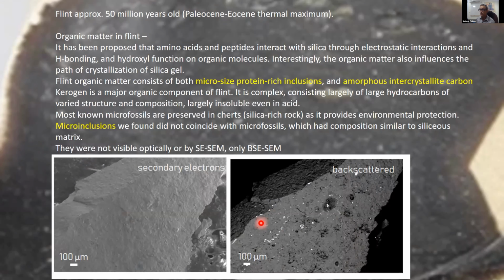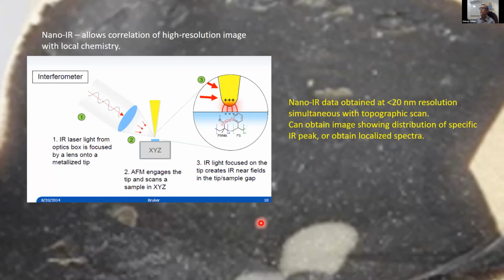The part that we're going to be talking about is these microinclusions. They're hard to see. You don't see them optically. You don't even see them in electron microscope with the secondary electrons, but you can observe them using backscatter. And that was used sort of to mark them off so that we could take them and analyze them using these scanning probe techniques. So we used two techniques.